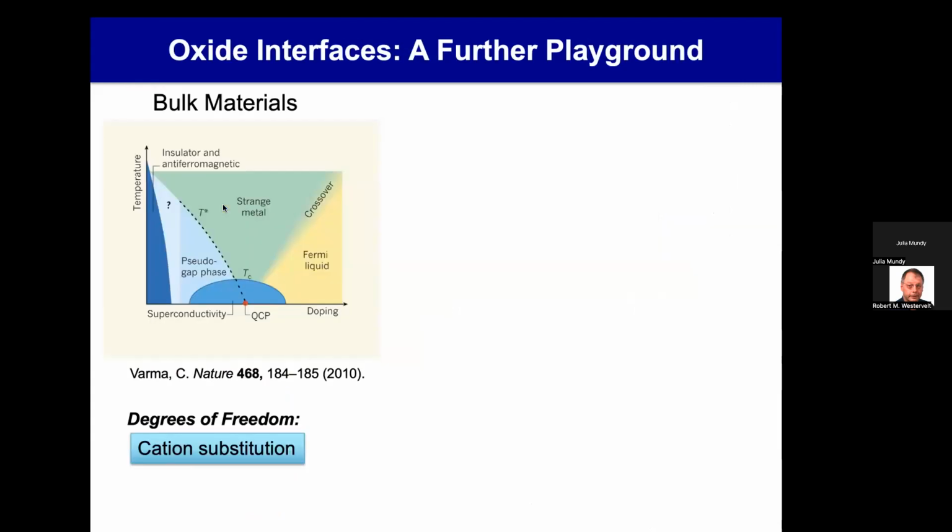Once again, lots of words which are not hidden. But the first thing is this is a phase diagram showing what electronic and magnetic properties can be found in this example of these cuprate materials, these copper oxide materials I showed on the first slide. The x-axis here is what we call doping. What that is physically in the experiment is taking a lanthanum 3+ ion and replacing it with a strontium 2+ ion. So you're varying the chemistry as you go across the series. The y-axis is temperature, so we can see that some of these really cold quantum phases only emerge at lower temperatures.